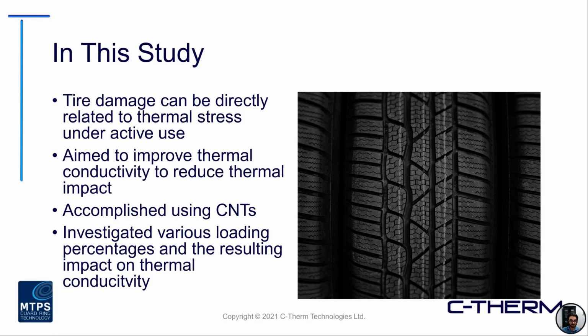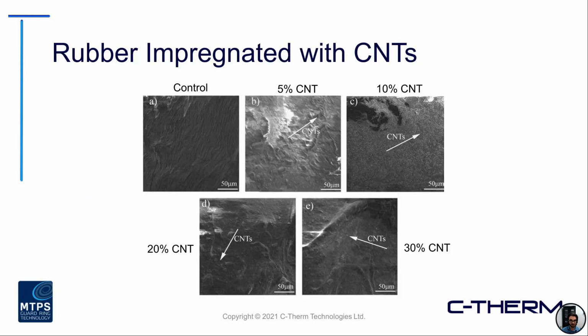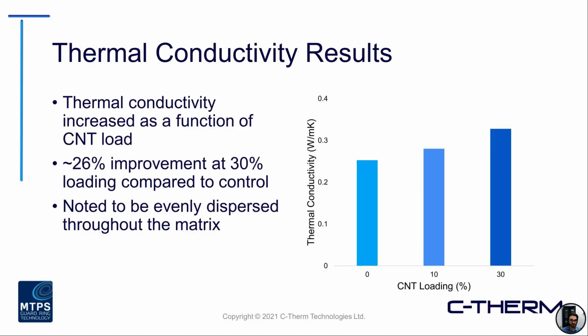So these investigations were done on different loadings of carbon nanotubes into the composite matrix. The rubber was impregnated with CNTs at different weight loadings. So you can see 5, 10, 20, and 30%. Based on the SEM images here, the CNTs may be more pronounced at the upper loading. But what they found was, as you would expect with the higher loading of CNT, this resulted in an increased thermal conductivity. There's about a 26% improvement at the 30% loading compared to that control.